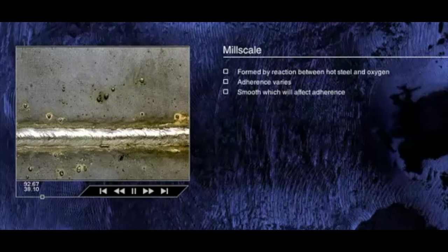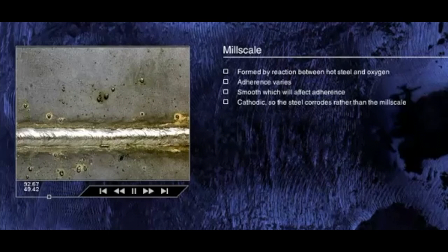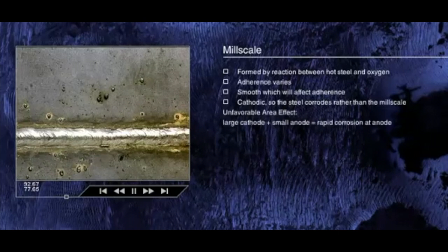Mill-scale is also relatively smooth, a factor which is significant for today's high-build, fast-drying coatings. Adhesion of coatings to smooth mill-scale may be poor, resulting in failure through loss of adhesion. Mill-scale is cathodic relative to bare steel. When steel is partially covered in mill-scale and exposed to corrosion, the cathodic mill-scale does not corrode, being protected by the anodic steel. Corrosion does take place at the anodic surface, and base steel is lost. This effect is the opposite of what is generally required.